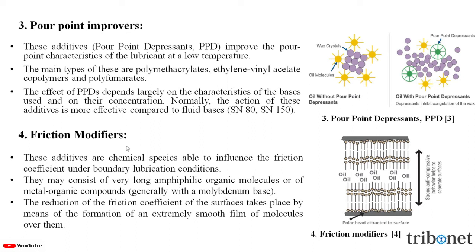The third one is friction modifiers. These additives are chemical species able to influence the friction coefficient under boundary lubrication conditions. They may consist of very long amphiphilic organic molecules or organo-metal organic compounds, generally with a molybdenum base. The reduction of friction coefficient of the surfaces takes place by means of the formation of an extremely smooth film of the molecules over them.